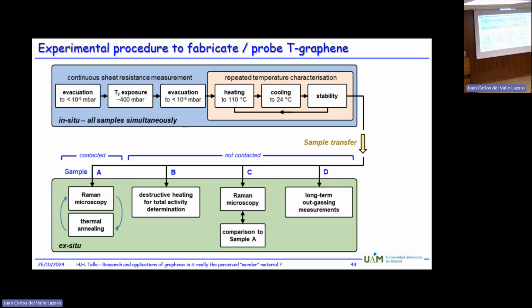So the procedure of all that is that first you expose the sample to tritium for a given number of hours, and then before you can analyze the samples, you have to make certain that everything which is physisorbed in the system is actually taken out. And as I said before, probably you remember one of the slides, the chemical bond only is broken if you go beyond 400 degrees, but those physisorbed van der Waals bonded molecules disappear already with low temperatures. And if you go, for example, to 100 degrees, more or less you achieve that all the physisorbed tritium disappears.